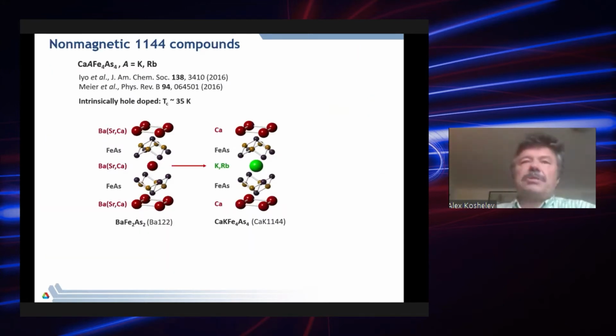Further develop, so all these materials I discussed so far are obtained by random substitution. But it turns out it's possible to create also stoichiometric materials by substituting every second layer with either potassium or rubidium. Then we obtain so-called 1144 materials, which are stoichiometric and intrinsically hole doped. They have superconductivity around 35 Kelvin.